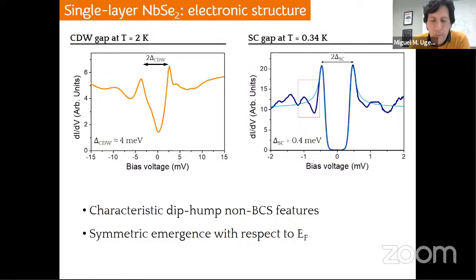But when you go to the Bogoliubov quasiparticle region outside the gap, things start to be a bit more strange, because they don't decay monotonically. What we normally see are these characteristic dip-hump features that are repeated more or less periodically outside the gap and, in general, not always, but in general, are symmetric with respect to the Fermi level. So these are non-BCS features that we have investigated further.